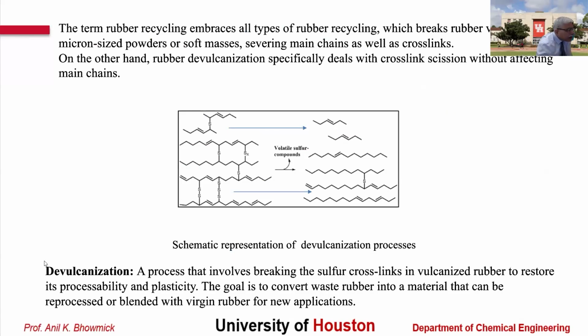The term rubber recycling embraces all types of rubber recycling, which breaks vulcanized rubber into micron-sized powders or soft masses, severing main chains as well as crosslinks. On the other hand, rubber devulcanization specifically deals with crosslink scission without affecting main chains. This is shown in the schematics here, and you can see how the crosslinks are broken down without affecting the main chain. This is called devulcanization, and this is really a challenge. So devulcanization is a process that involves breaking the sulfur crosslinks in vulcanized rubber to restore its processability and plasticity. The goal is to convert waste rubber into a material that can be reprocessed or blended with the virgin rubber for new applications. Next slide, please.